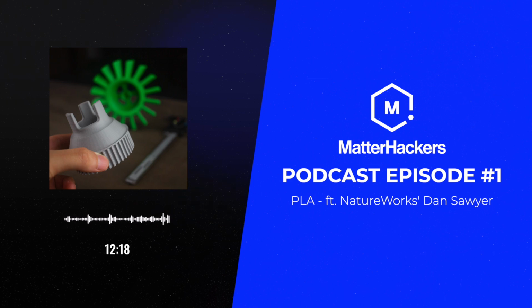And with the toughness, we kind of talk about two. One, where a lot of companies have added a little bit of additive into their filament to make it easier to process. But on the other end, we've really impact modified with some of our grades that we've developed specifically for 3D. Around 2015, we really started focusing on developing grades specific for 3D, and we were able to take advantage of what we really struggled with in some of the other areas like injection molding in improving the properties, and inherently was easier to use some of those tricks we learned there in 3D printing than it was in injection molding, actually.